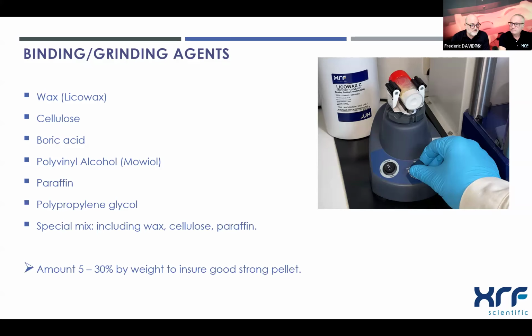And of course, this is something you need to verify before going to the spectrometer. So it's good to, for example, drop the tablet on the table from 10 centimeters, just to check that the pressed powder tablet is strong enough before going to the spectrometer. And maybe you can remove a little bit of the dust you have around the aluminum cups, for example.